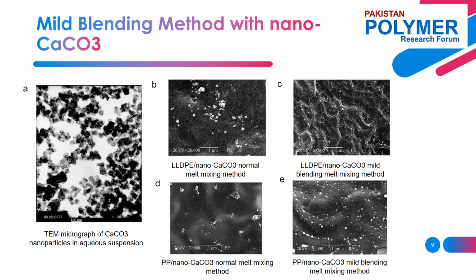The dispersion of nano calcium carbonate particles in the matrix was assessed by SEM, as shown in figures B, C, D and E. Figures B and D show the SEM photographs of nanocomposites of LLDPE and nano calcium carbonate, and PP and nano calcium carbonate, formed with the normal melt mixing method. The particle aggregation in this material ranged in length to about 0.5 micrometer because the shearing force was not enough to break the nanoparticle aggregation in the melt.